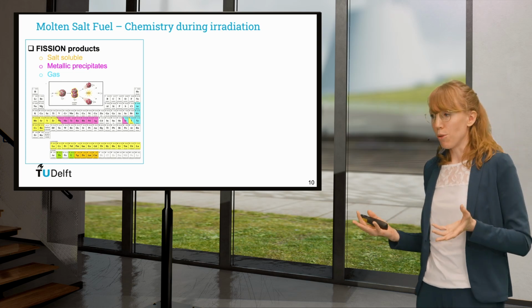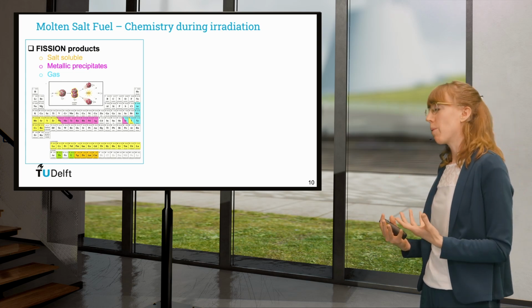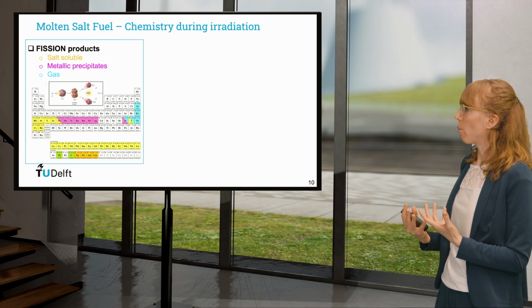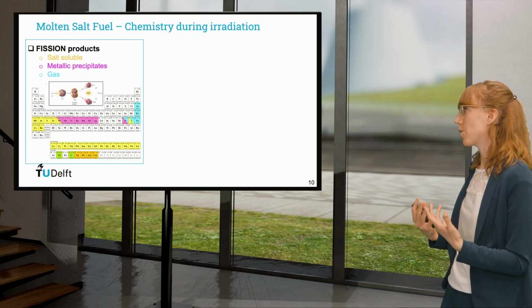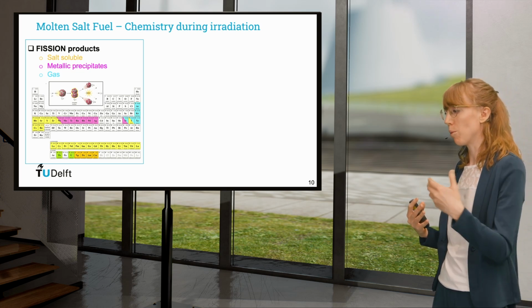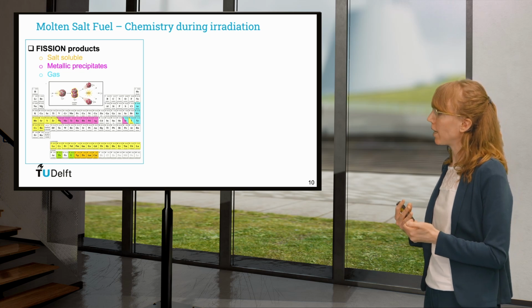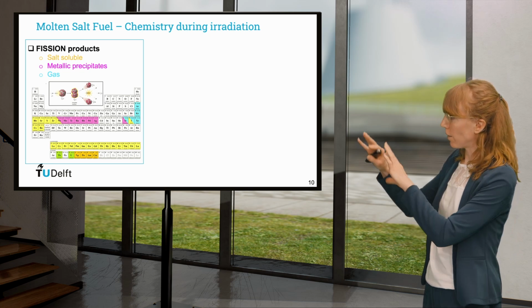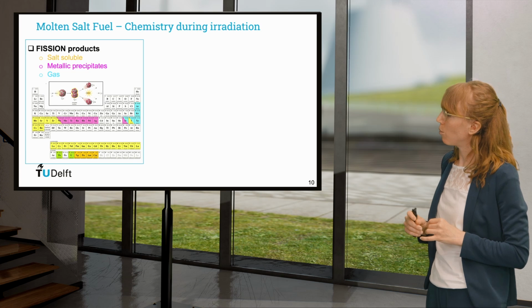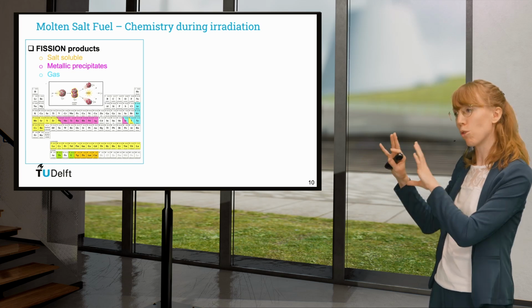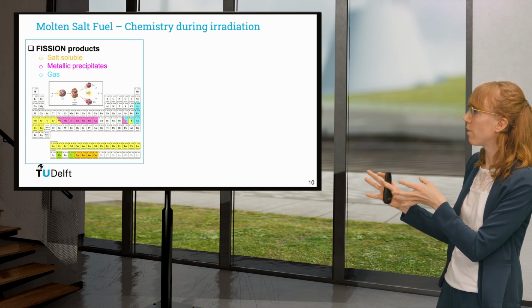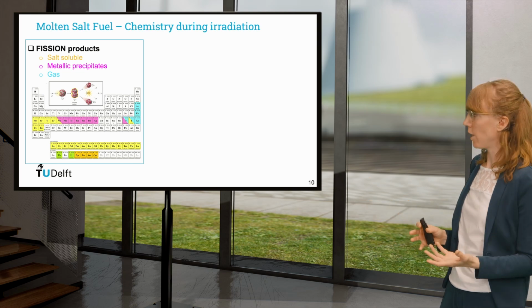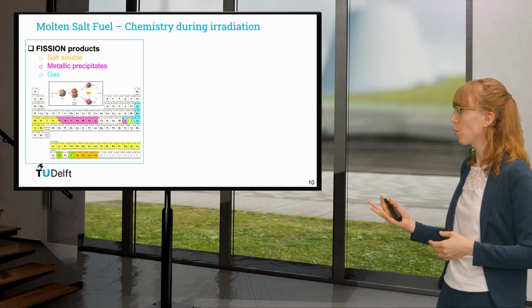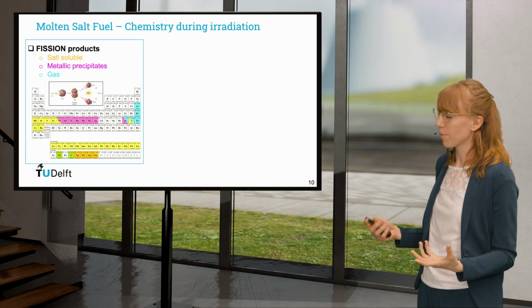This is the starting fuel, but once you put it in the reactor, things become more complex. First, you have a fission reaction. And that means that you will be generating fission products during irradiation. You can see these fission products on the periodic table of elements. They have colors, and already you see there are quite a lot of them. They can be soluble in the salt, or they can form metallic precipitates or be gas.